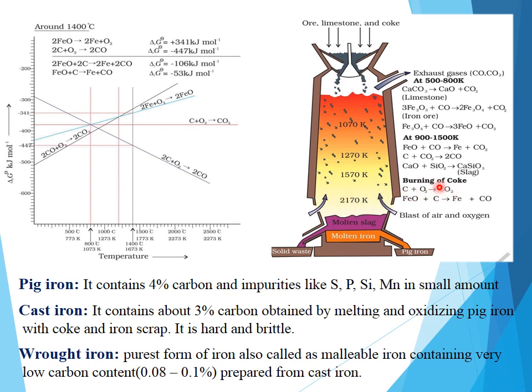Once this carbon dioxide is formed, it moves to the upper part of the furnace, where it will react with some more coke and form carbon monoxide. This is the main important requirement because it is used as a reducing agent over here. This carbon monoxide is formed when the carbon dioxide produced combines with coke, and it is an endothermic reaction. The temperature will reduce at the top regions. So at the lower region the temperature is high, and at the upper region the temperature will be low.